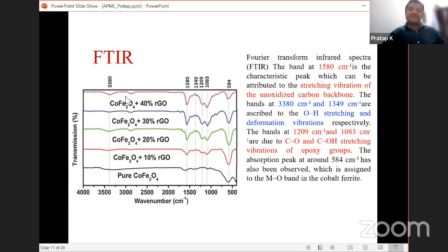This is the FTIR data. Black is pure cobalt ferrite, then 10% RGO with cobalt ferrite, 20% RGO, 30% RGO, and 40% RGO with cobalt ferrite. You can clearly see that the peaks are prominent. There is a peak at 1580, which is a characteristic peak of the stretching vibration of the unoxidized carbon backbone.